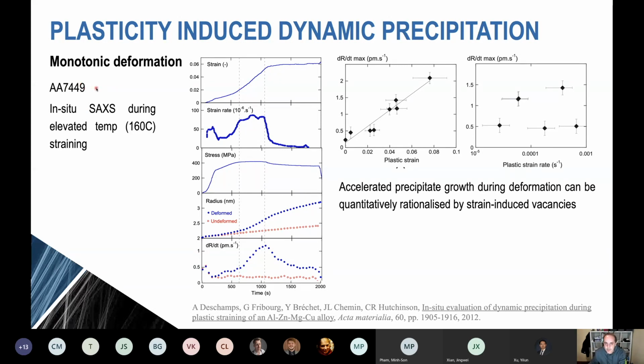And this was an experiment where we performed in situ small angle X-ray scattering at a synchrotron at elevated temperature and strained the material at the same time. And we wanted to examine the effect of that plasticity on the growth rate of the precipitates. And so the interesting things here is to look down here at the radius. So this is the radius comparing deformed and undeformed particles as a function of time. And the blue is during straining and the red is without straining. So it's clear we have a very obvious acceleration of the precipitation process, in this case, the precipitate growth process